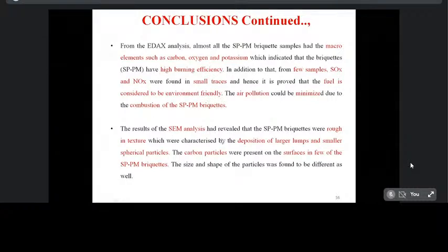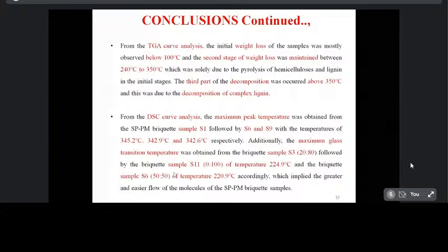The results of SEM analysis revealed that the sorghum panicle and PM briquettes were rough in texture, with deposition of larger lumps and small spherical particles spread over them. Carbon particles were present on the surface in a few of the sorghum panicle and PM briquettes. The TGA curve is also used to find the weight loss. The initial weight loss was achieved at less than 100 degrees Celsius because of reduction of moisture content, and from 240 to 350 degrees Celsius the pyrolysis of hemicellulose and lignin was observed in the initial stages. The third part of the decomposition occurred above 350 degrees Celsius during the decomposition of complex lignin.